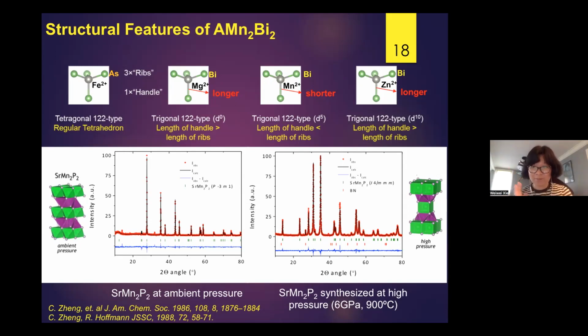Very interesting: after we treated it for half an hour, we found that strontium manganese 2 phosphorus 2, which at ambient pressure is the trigonal phase, becomes the tetragonal phase after high-pressure treatment. After I did this experiment, I was like, oh yes, that's so cool. Now we can study these systems, and we think a lot of interesting things will happen.